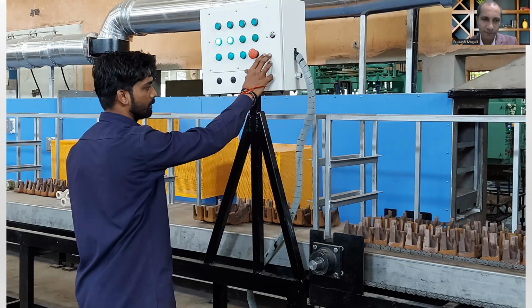In fact, there was one foundry from Kolhapur who was not interested in paint drying, but they were interested in reducing the moisture in the core itself. Okay, great. And so they are using it for this purpose. Yeah. So in the same oven, they passed the CO2 based cores, where the silicate that was used had moisture, and that moisture was creating a problem. So we did some trials in the oven, and it can reduce the moisture in that oven also. There was no paint involved, just the moisture in the core.